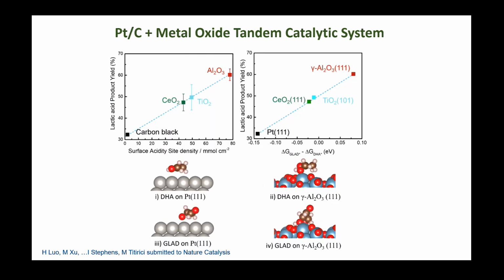So we looked at the pure carbon black and the platinum supported on carbon black, but then also on cerium, titanium, and aluminium. And we correlated the surface acidity density of all these supports with the lactic acid production. And we've seen a very linear correlation, which is also confirmed by DFT if we look at the production of dihydroxyacetone on alumina, which has the acid sites. We could see also this very nice correlation.